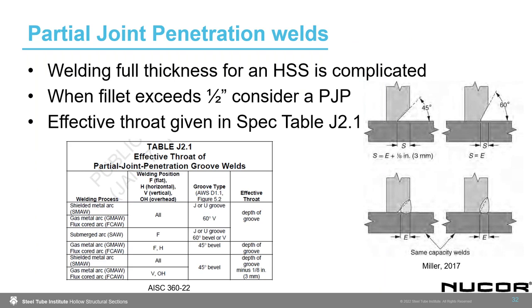PJP welds are something that I hope we can employ more often, as they can be a much more economical solution rather than going straight from a large fillet weld to a complete joint penetration weld. CJPs require backing and specially qualified welders, so it's a reasonable consideration to look at partial joint penetration welds. Welding full thickness for HSS is just complicated. The effective throat for those PJP welds is given in the specification in Table J2.1.